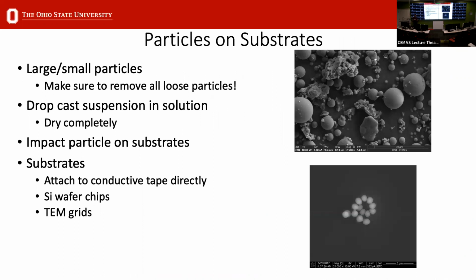So I didn't start with this, but in many cases, the easiest way of preparing any type of sample is, if you have particles, just disperse them on a substrate, or you can disperse them on a tape on an aluminum stub. If you have small enough particles, you can disperse them on a substrate like silicon, or you can put them on carbon tape. You just want to make sure that you remove all the loose particles before you put it in the SEM.